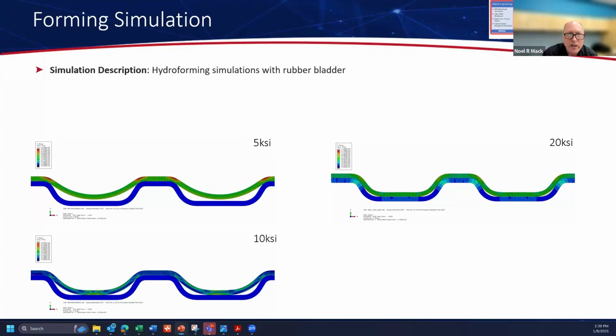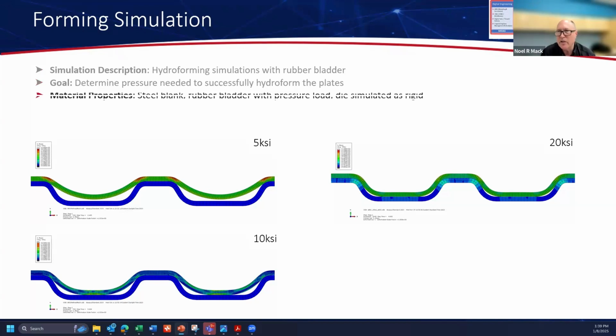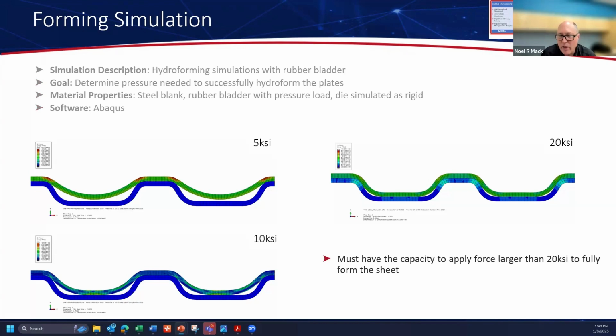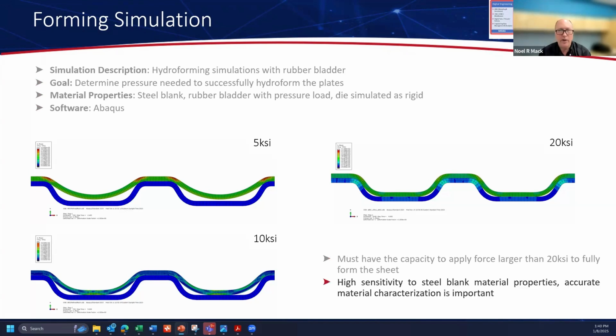From the simulation perspective, we're looking at the hydroforming simulations of the rubber bladder to form these foils, determining the pressures that we need to fill the tool with the foil to form the plates. In this case, the steel, using a steel blank, a rubber bladder with a pressure load, and then the die is simulated as a rigid body, and we're using Abaqus in this case. We obviously need the capacity to fill the void, and we found we need roughly 20 KSI in the hydroforming system to be able to fill the tool, should I say.